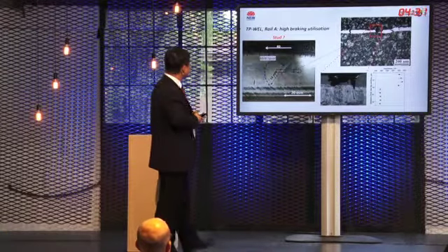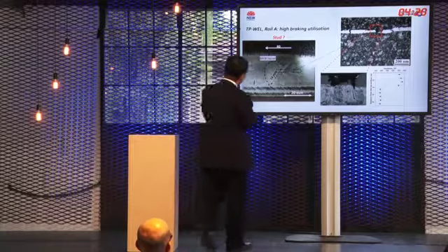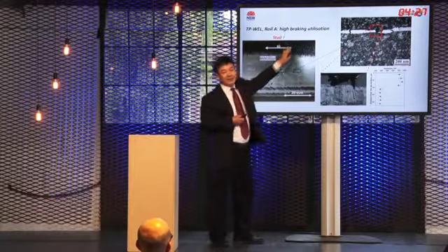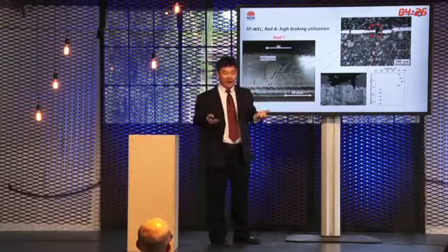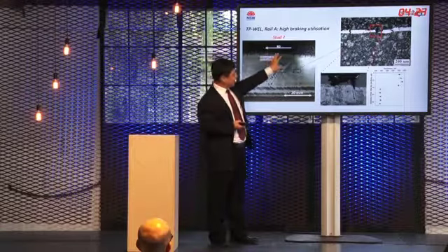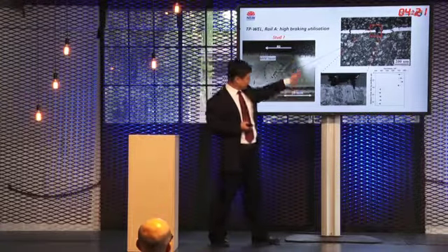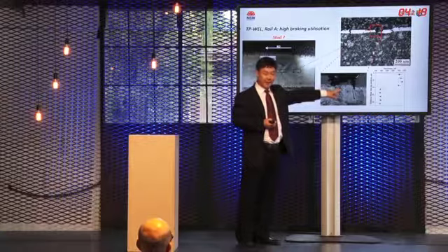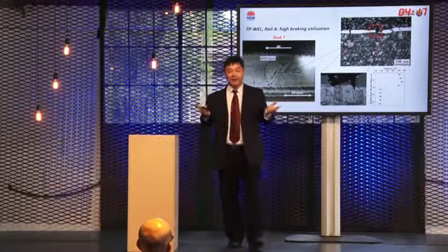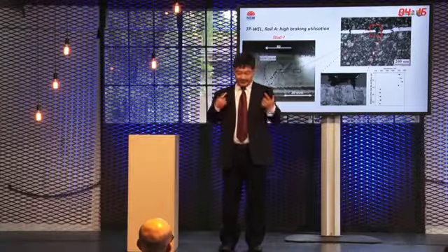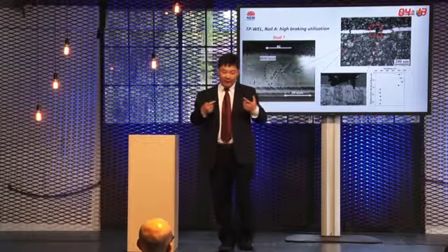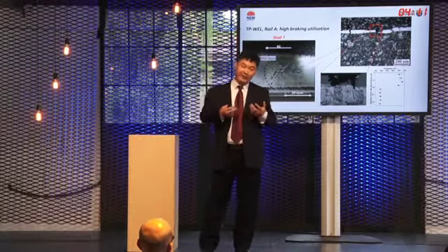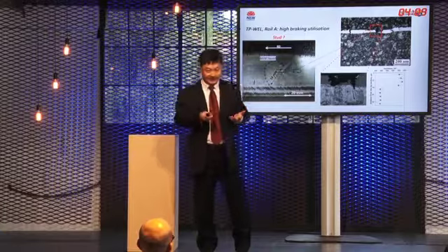Now, let's go back to this. I know this morning we had lots of discussion about studs or squats. Actually, checking this kind of white etching layer, the induced crack structure perfectly fits the definition of the stud. This is why we believe that in the network, lots of defects are stud defects.